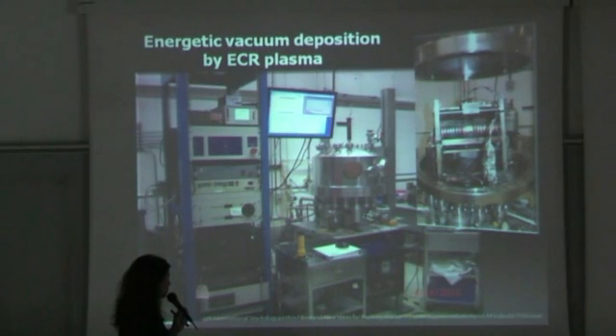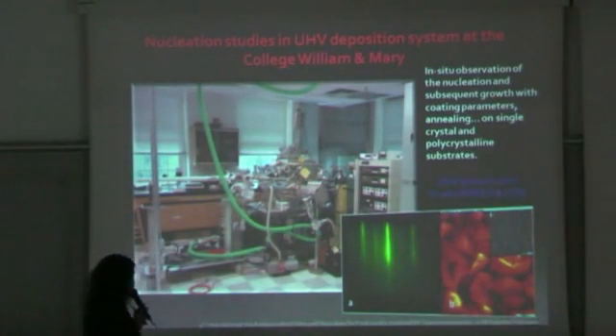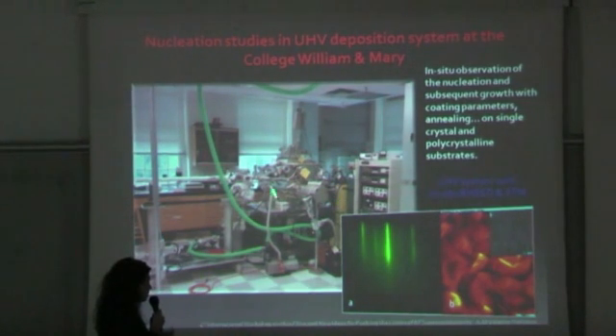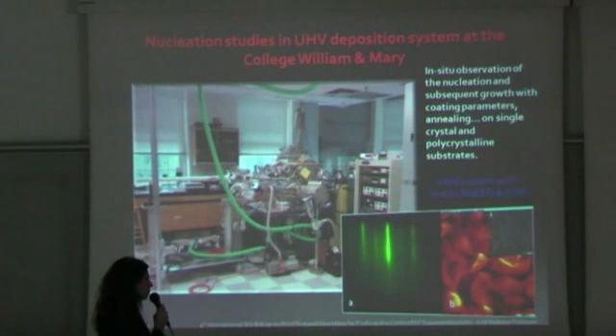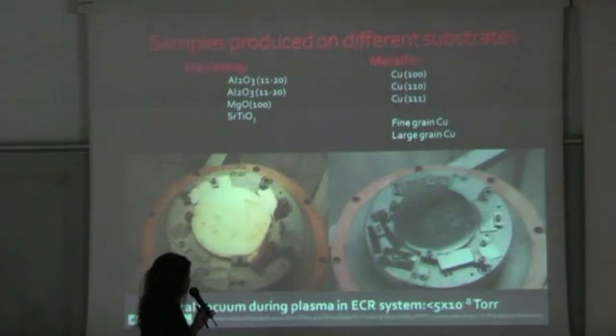This is a picture of the system showing the inside of the chamber — you have the E-beam gun, the coil, the waveguide, all attached to the ECR chamber. This other setup is at the College of William & Mary — it's a UHV deposition system based on sputtering. The advantage of this system is that it has an in-situ RHEED and will have an in-situ STM, which is very useful for studying epitaxy of niobium or whatever film you're growing on a substrate — for example, when depositing on copper to do epitaxy, it allows you to see when you have completely reduced your oxide layer.